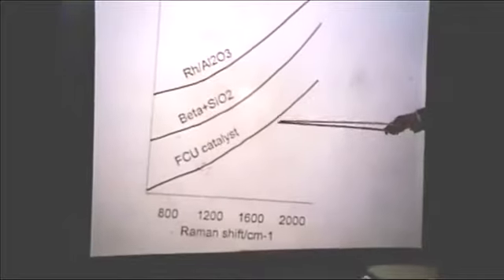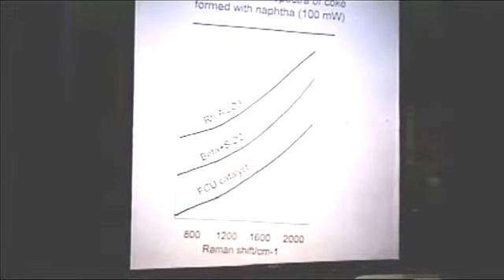Well, so we wanted to be sure that this wasn't a fluke, and so we looked at the other samples that they gave us, and this is just a representation. This just shows 3 different ones, including the rhodium on alumina. There was also a beta silica and a fluid cracking unit catalyst, and this is what you see in the green. That is, you see nothing, you just see fluorescence. And when you look at these samples in the UV, you get beautiful Raman spectra